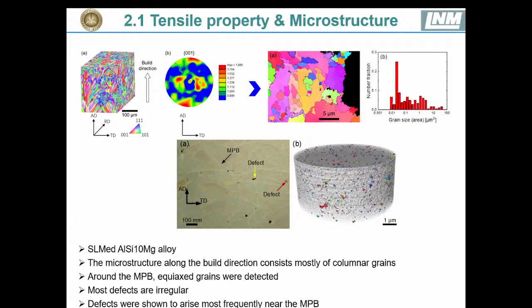And here we can see that both columnar grains and also equiaxial grains were observed. And also we can see some irregular grains and also some defects are shown most frequently near the molten pool boundary here, showing this figure. And also we can see some distribution of the grain size of this material here.